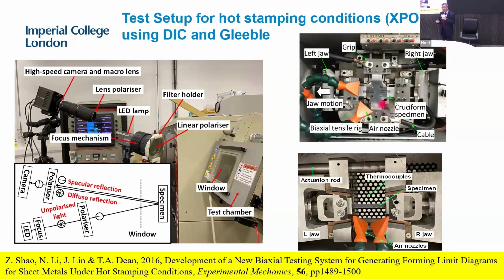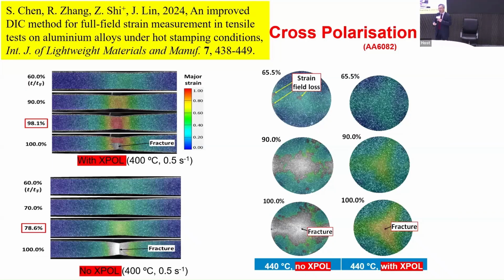But the problem is that when the material is close to failure, the paint disappears or peels off, then it's difficult to get the data at a later stage of the deformation. This is crucial. Previously, it was difficult to get data after 60% of the deformation, and it's difficult to judge. Then we developed the cross-polarization method. We call it the XPO method. The XPO method gets rid of the reflections, removes these kinds of problems, and gets the data.